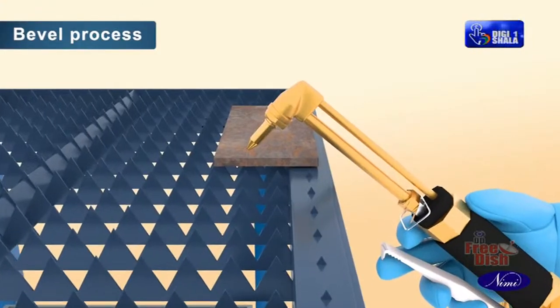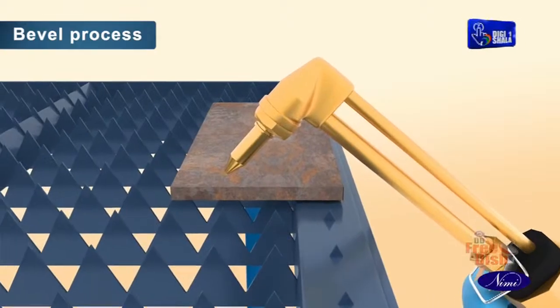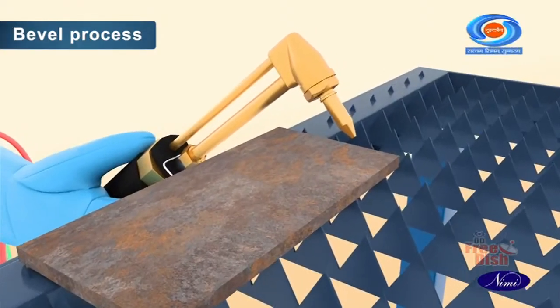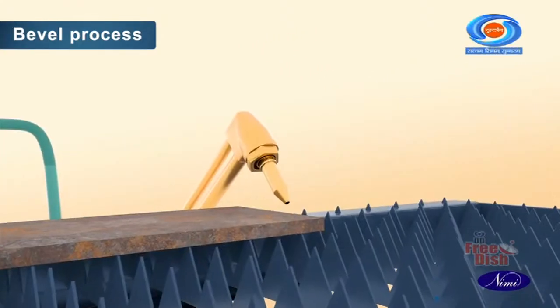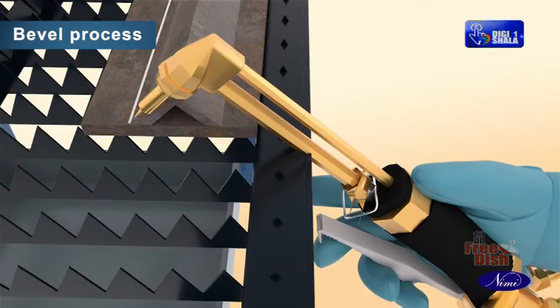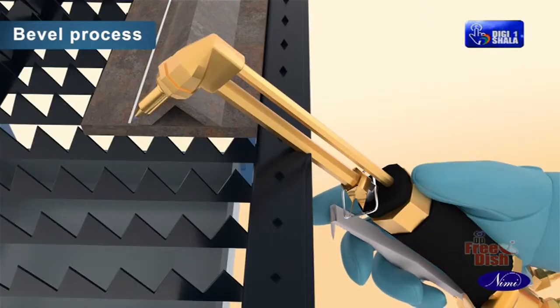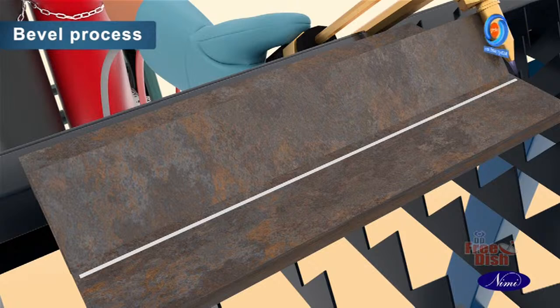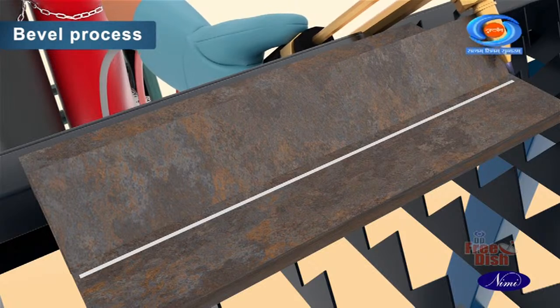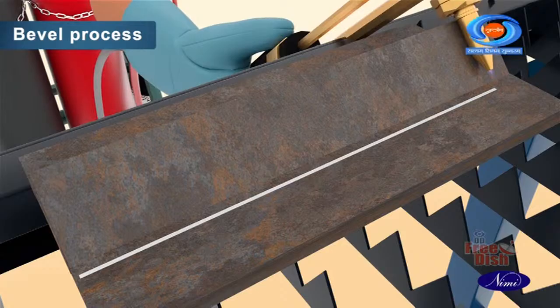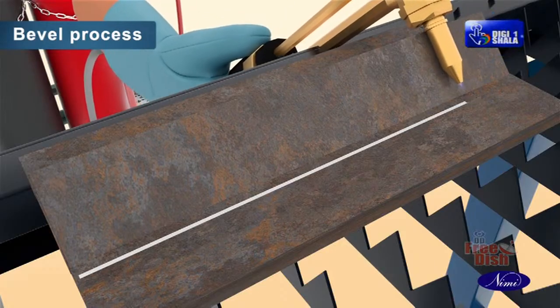Distance between the workpiece and the nozzle tip should be maintained as in straight cut to avoid backfire. Release extra oxygen, observe the cutting action, and start traveling along the punched line with a uniform speed and steady hand.